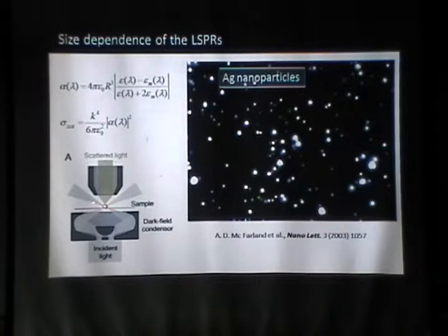But if there is anything scattering light, then it will scatter light. So the trick here is that we collect light with a numerical aperture smaller than our illumination numerical aperture. So none of the light that we use to illuminate goes to our detectors, unless there's something scattering on the sample. That's why the background looks dark, but where we have some scattering point, then we see light. And those scatterers here are silver nanoparticles. And if we use white light to illuminate, then we see that these nanoparticles shine up with different colors. And the reason for those different colors is the different sizes.